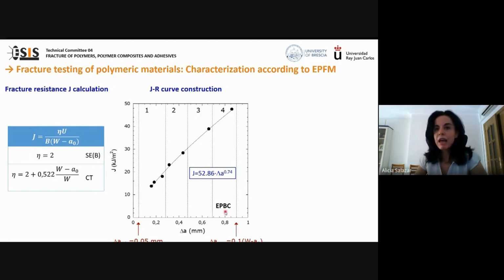There are 2 exclusion lines in red, one at 0.05 millimeters. Only the data beyond this line are considered valid, and the other one is at 0.1 times the initial crack ligament. Beyond this limit, the J values may not be valid. To ensure that the data points are evenly spaced, the interval between the 2 exclusion lines is divided into 4 equal sections. Since there is an interest in determining the fracture toughness or the fracture initiation parameter, 3 points are recommended in the first section, 2 in the second, and 1 in the third and fourth section.